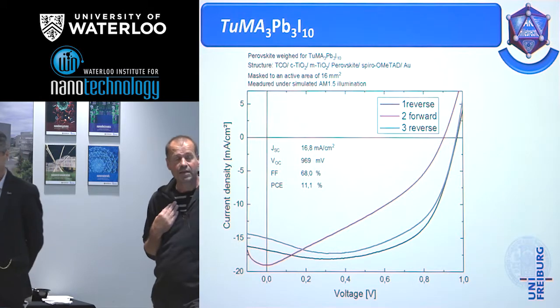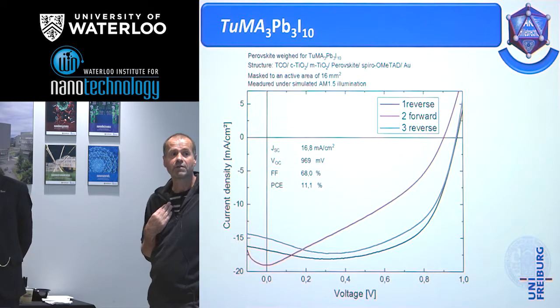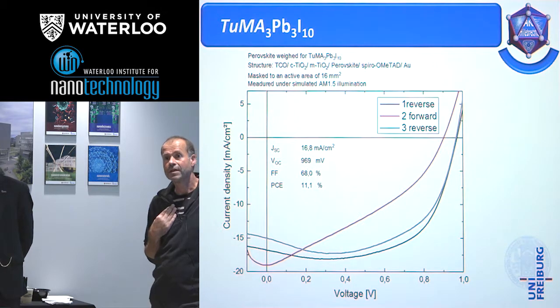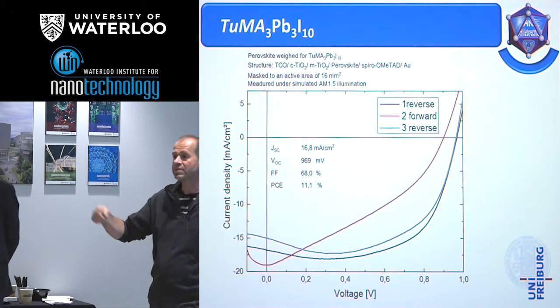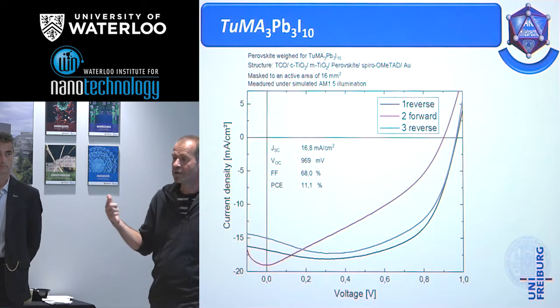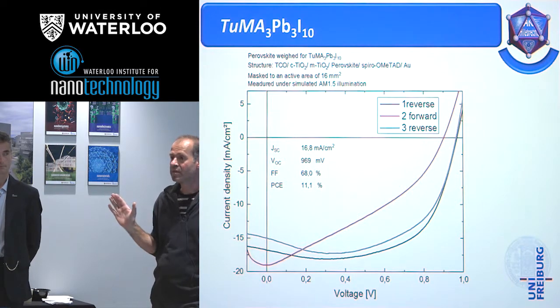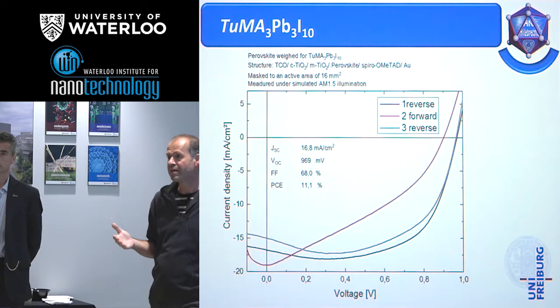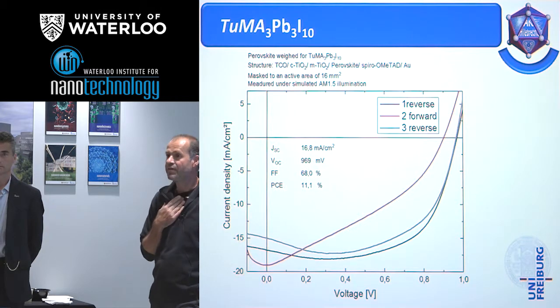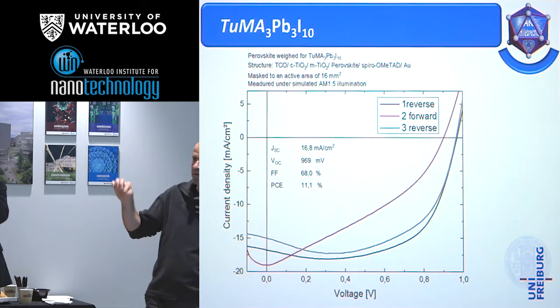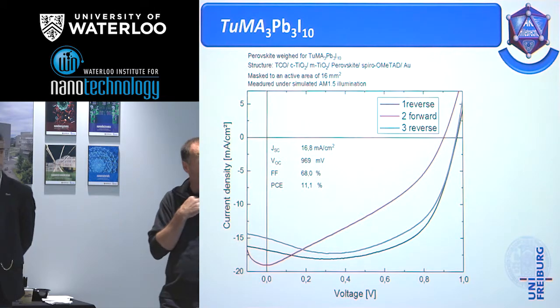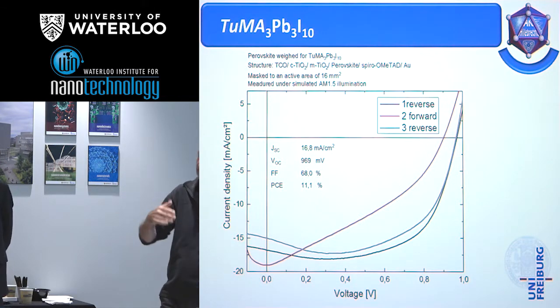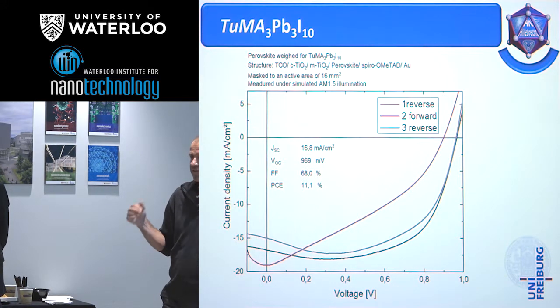I agree that small amounts of thiocyanate give a better stability against hydrolysis, but probably not because of a substitution within the structure. Because I don't know any example where you have the substitution of iodine by thiocyanate. No, I don't know any example. Nevertheless, small amounts can change the way of the precipitation. And for example, it is very well investigated for the case of the substitution of iodine by chlorine. In the first paper and many other papers, it is stated that there is a solid solution.